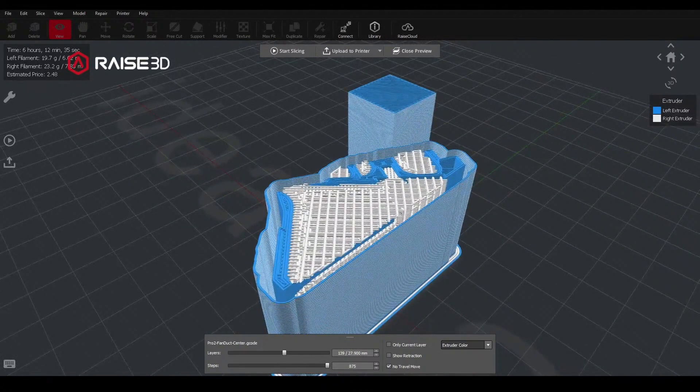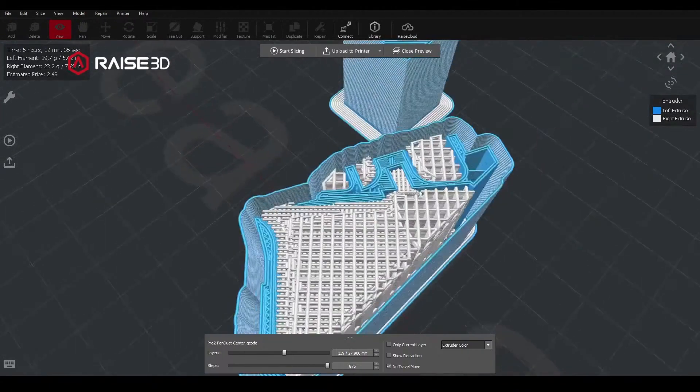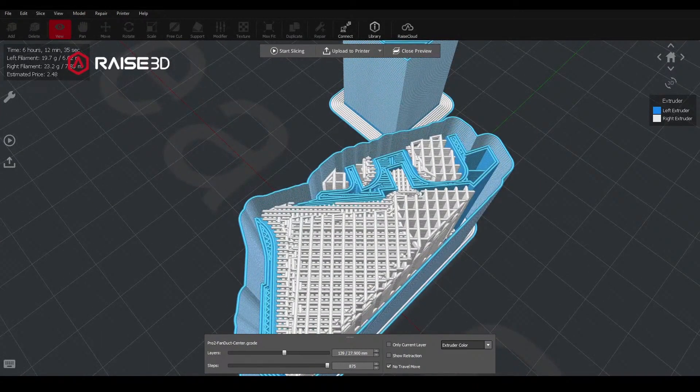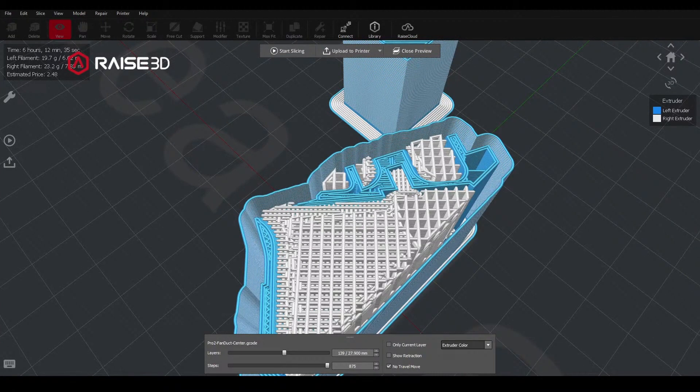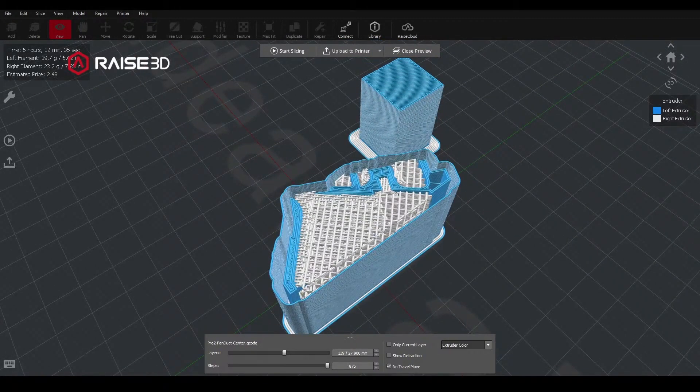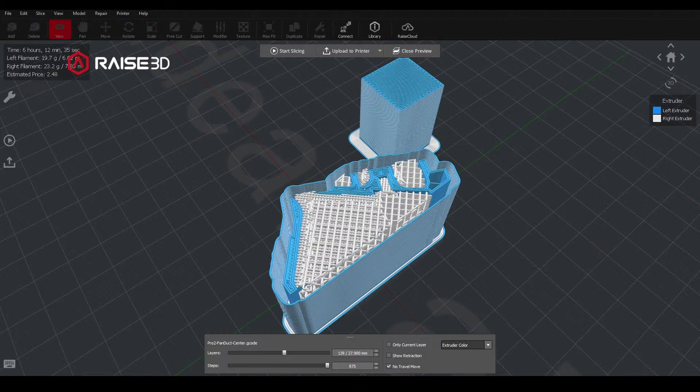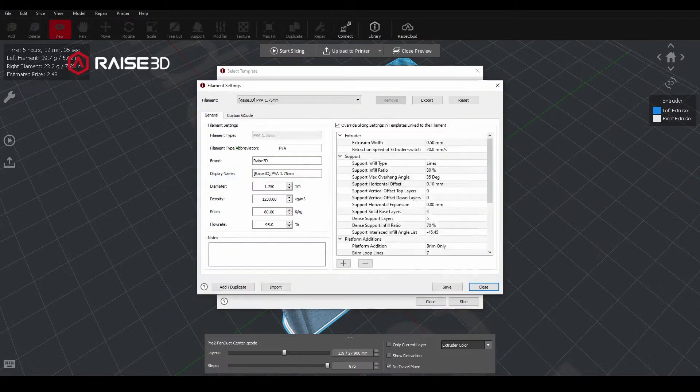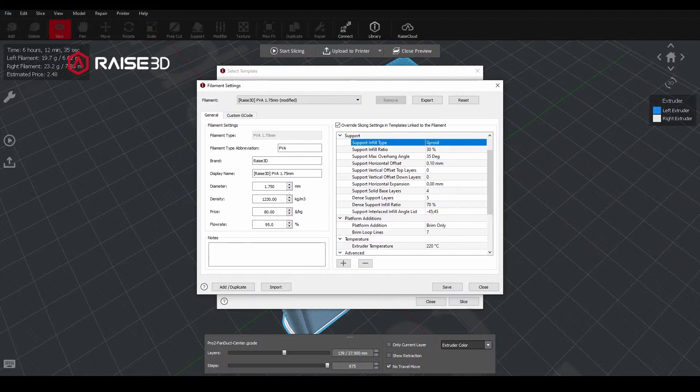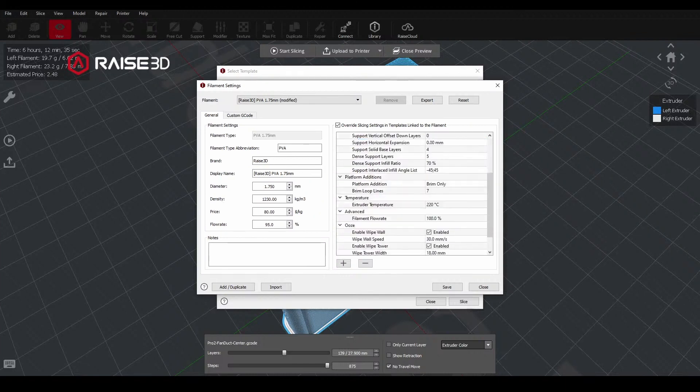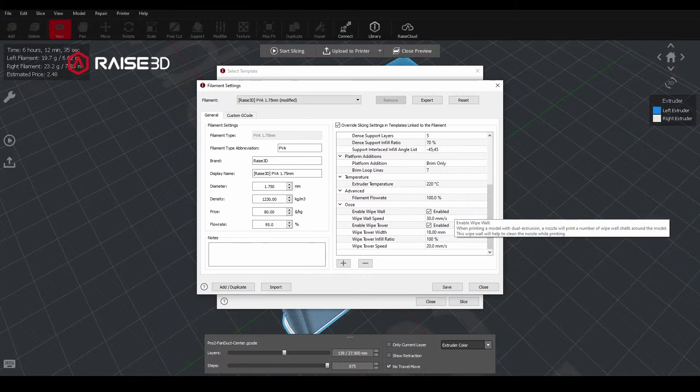Working with the other PVA materials, by default it is set to a line pattern for the infill. It actually, in my experience, will dissolve faster if we set it to a gyroid pattern. It just allows water to actually get in through all the support structures and dissolve it all at once rather than trying to break through those grid walls. So when we go back in here under the right extruder, I'll change our support infill type to gyroid. And we'll keep the infill the same. The brim should stay that way. And then we'll also keep the wipe wall and wipe tower enabled. But if you wanted to disable them, this is where you would change those.